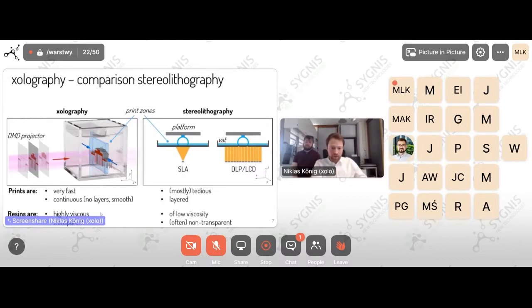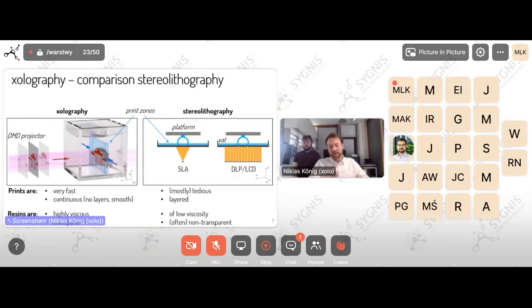But to be frank with you, our technology also comes with one limitation, and that is our photopolymers have to be absolutely transparent, because it relies on the intersection of two light beams. And you could imagine that if we have a hidden absorbing species in the volume, then the intensity would deviate depending on the penetration depth. And this would result in different kinetics depending on the space coordinate where you are in. And this we would like to avoid, to have a homogeneous print. So our resins need to be transparent, while in standard stereolithography you can also have non-transparent photoresins, as the printing zone is so small and you just have to shine light through like 50 microns.